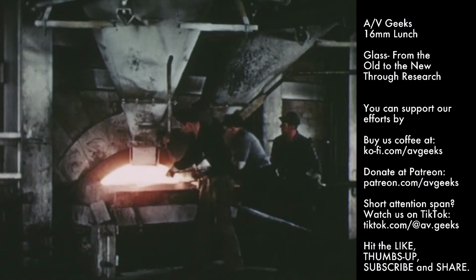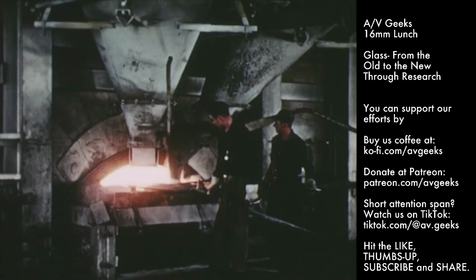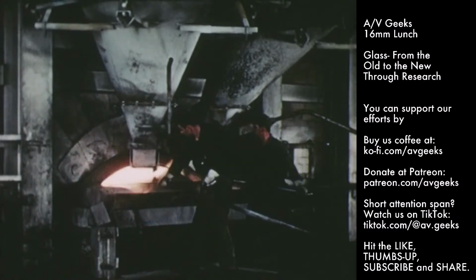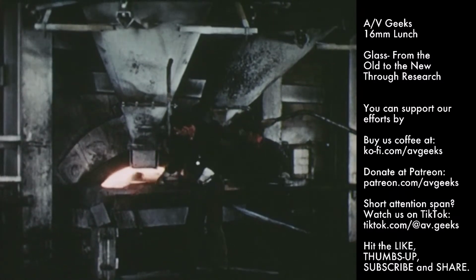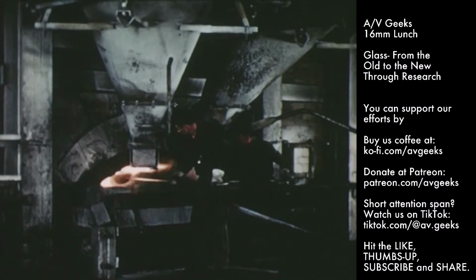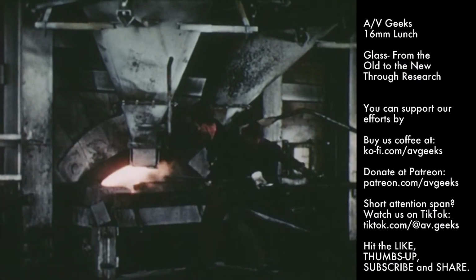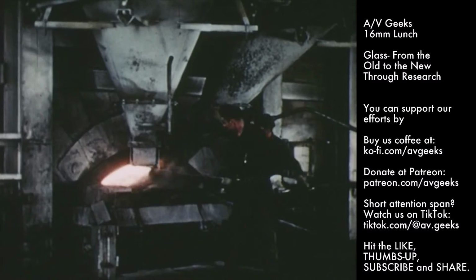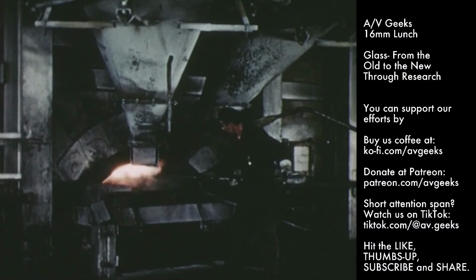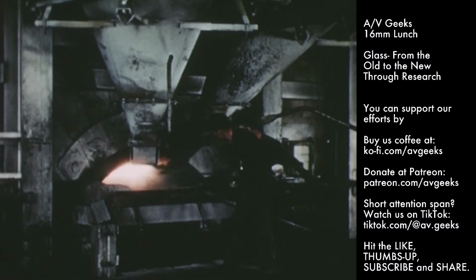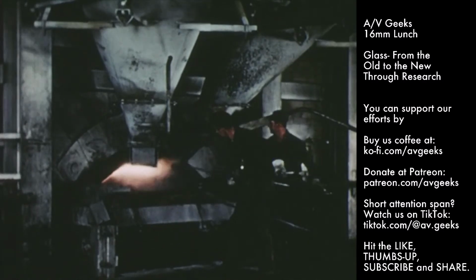A large furnace like this may hold several hundred tons at one time. Heat released by burning gas produces a temperature of about 2,700 degrees Fahrenheit. The heat transforms the mixture from its solid form into a molten, sticky mass.